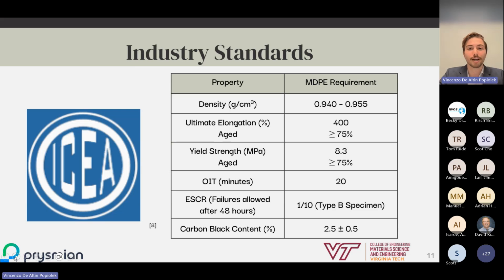Our industry standards are provided to us by the Insulated Cable Engineers Association. There are different requirements for each different density of polyethylene. The MDPE requirements are highlighted here as that was the target density for our final sustainable blends. In order to be considered MDPE, the density of the polymers must lie between 0.94 and 0.955 grams per centimeter cubed. The ultimate elongation must reach at least 400% and retain at least 75% of its original performance after aging for 7 days.